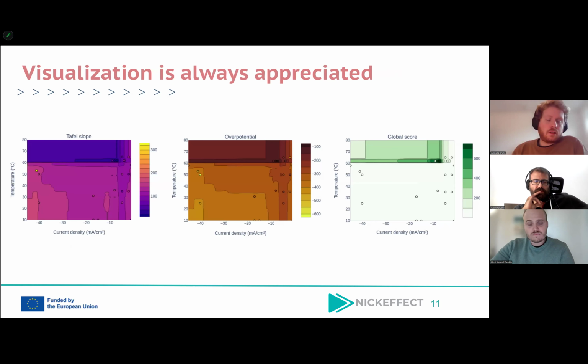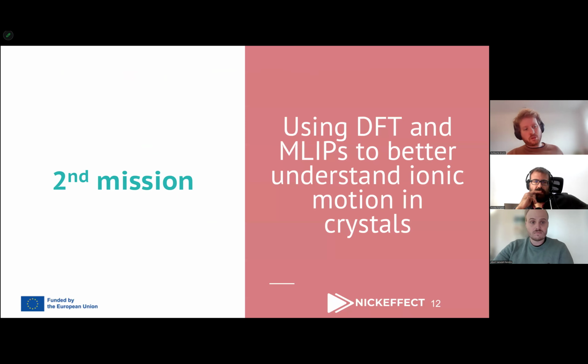And another thing that I wanted to add is that using a machine learning model to model a process like this can also help by bringing insights into what happens. And so this is done usually through visualization. For instance, here you can see how the Tafel slope, how the potential, and how the global score evolve with the temperature and the current density. And so you can see here that there's really a sweet spot for the score in terms of temperature and current density, that you should aim for if you want a high score. And this really can help bringing insights and understanding using the machine learning model. Okay, so that was the first example, the first small project.